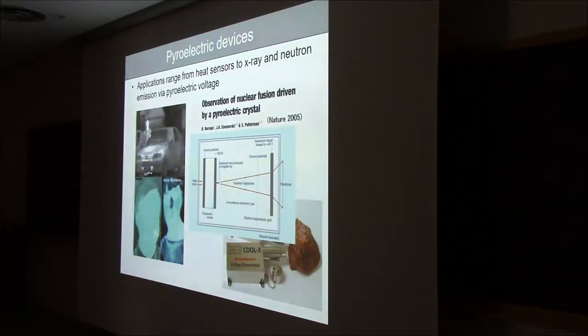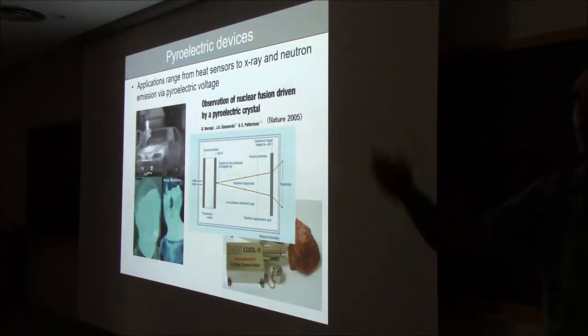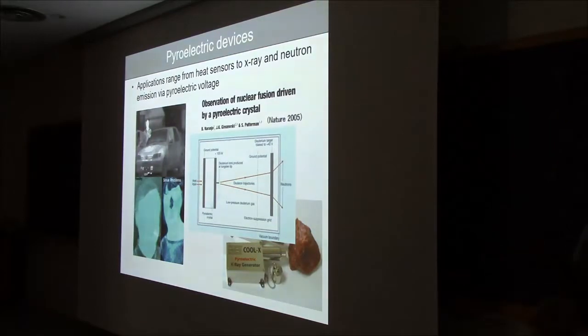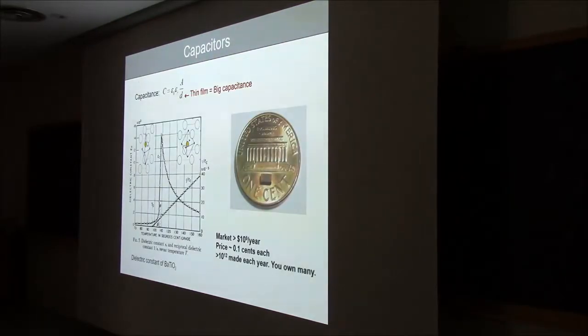You can also use it to induce pyroelectric fields that you can then use for field emission, and these turn out to be extremely high, because you can concentrate these pyroelectric fields, and apparently you can even create nuclear fusion with the ions that are ejected by this pyroelectric field. Okay, I think that's a curiosity. I don't think there will be atomic bombs made with ferroelectrics. You needn't worry, but just to say that pyroelectricity is real and it is used.